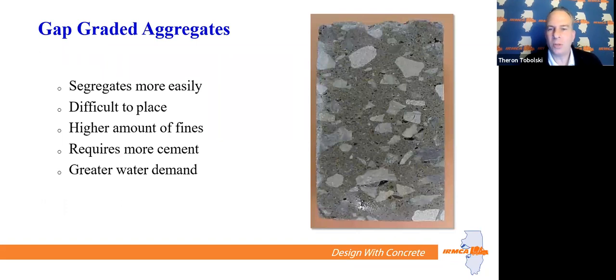Gap graded aggregates, as you can see here from this slice of concrete, have the very large sizes and small sizes. This type of concrete would segregate more easily. It'd be difficult to place. It would have a high amount of fines. It would require more cement, and it'd have a greater water demand. So that's what happens when you have a gap graded aggregate that you use in your concrete.